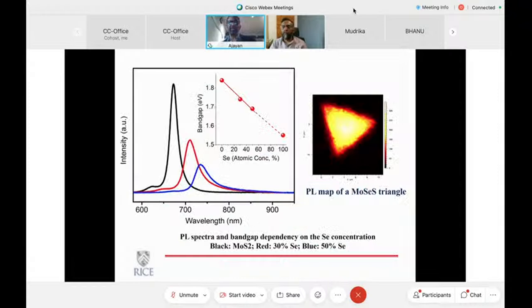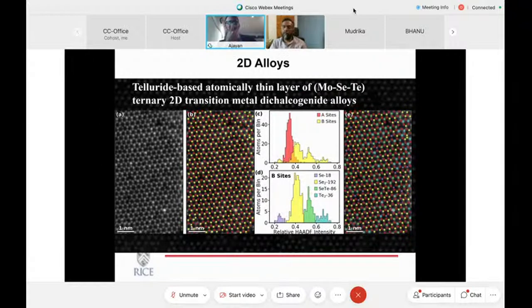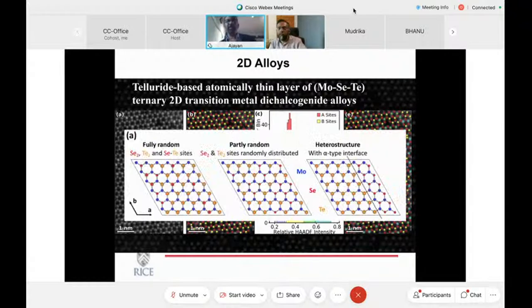And we were able to show that by changing the concentration of dopant, you could change the band gap by several hundred meV, which is a pretty good result. You can change the band gap reasonably by doping. But then, obviously, when you go to the three-component system, more towards the alloy at higher concentration of dopants, then you still have this problem of at what conditions would these be completely mixed or miscible, and at what conditions would they separate. It's almost like looking at a phase diagram of a 2D material. Which is, again, the same story with nanoparticles. The phase diagrams shift quite significantly, phase boundaries shift. So, again, there are multiple possibilities. You can have a fully random situation.